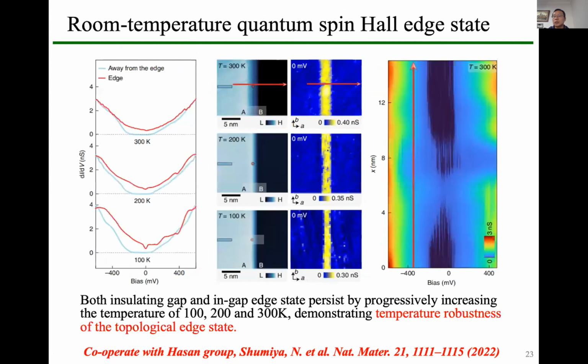Then we measured the temperature dependence of this dI/dV spectrum on the surface and the edge. The spectra here are offset for clarity. You see that at 100 Kelvin, 200 Kelvin, and 300 Kelvin, the band gap is still here. The in-gap states are also observed even at room temperature. So this means that the edge states are very robust against temperature. That means this material is very promising for room temperature devices of the quantum spin Hall effect.